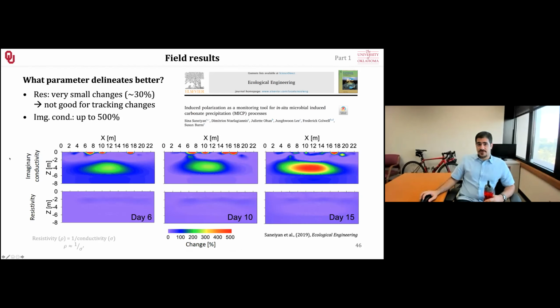And it failed to show calcite precipitation, because if you remember, resistivity is mostly sensitive to the pore fluid conduction, right? And we didn't change that at all because we used groundwater, mixed with a little bit of urea, which doesn't change the conductivity that much, and injected it back into the groundwater. If I use a time-lapse image, basically showing the changes over time, we are seeing that the resistivity is not showing that much change over time. So calcite precipitation is not as effective at increasing the resistivity as we expected. We are not injecting so much calcite that it pushes out all the water possible. We are injecting a little bit.